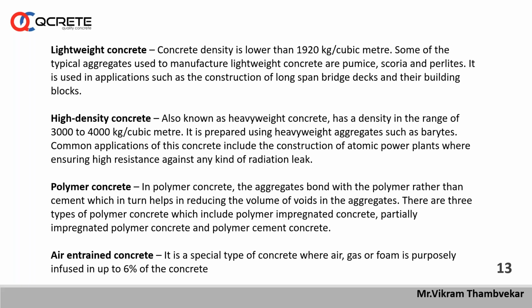Here I want to tell all the attendees that I have provided a design for lightweight concrete, which was used for making a canoe. The canoe was cast by some college students to send to a competition, an international competition in the USA. So we constructed one canoe with lightweight concrete in Mumbai, at Mukesh Patel Engineering College in Andheri. The canoe size was 450 mm wide by some 5-meter length, and the wall thickness of that canoe was hardly 40-45 mm. That canoe was tested in a lake. It was floating very well without any problem, without any leakage of water. And the density of that lightweight concrete was only 1100 or 1150.